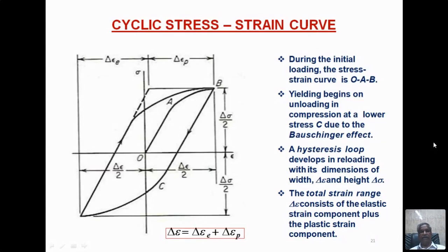But in low cycle fatigue, you have to fix the strain. What is the strain? What is the displacement? That you have to fix, 0.1 to 0.5. So you have to fix it in terms of strain. It's strain control. You cannot do low cycle fatigue in the high cycle fatigue machine. You need a separate machine for low cycle fatigue. Low cycle fatigue machines are strain control machines. Maybe tomorrow I'll give the photographs and other things. So for low cycle fatigue, you require a strain control fatigue testing machine.